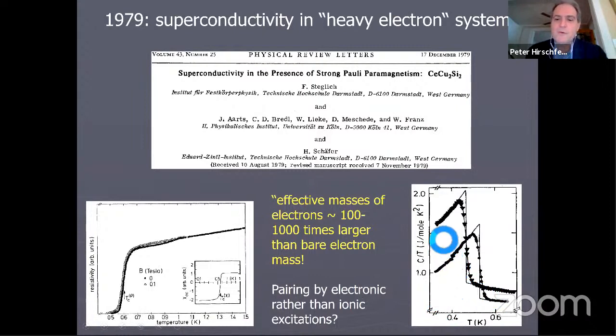They're in joules per mole Kelvin squared instead of the usual units that you see in specific heats of simple metals, which are millijoules per mole Kelvin squared. And the superconducting jump scales with this enhancement of the mass. And so if you have such large mass electrons, the argument I gave you about the retardation of the superconductivity does seem to be a little bit challenged. And so that's why it was surprising that this was discovered.